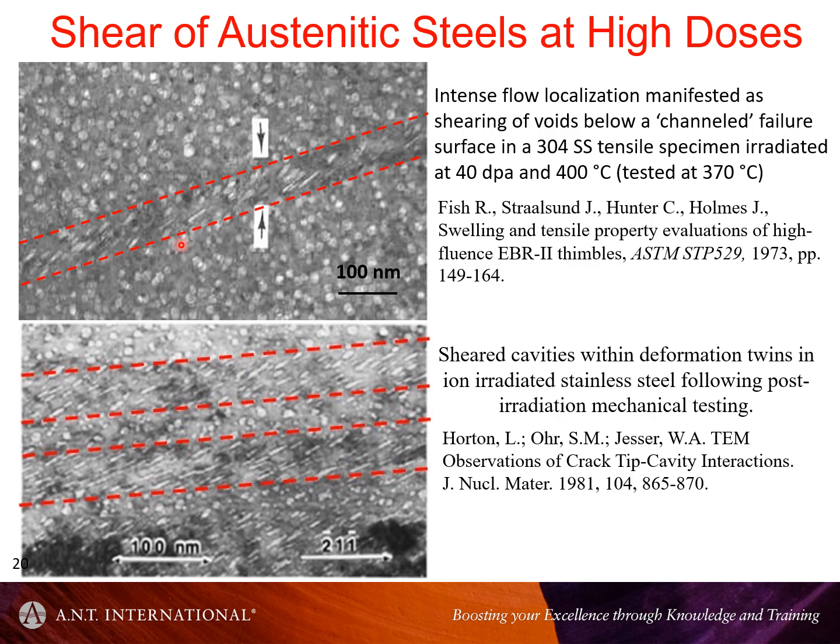You'd not see the twin material, because the first twin would go through, shear the cavities, and then let's say another twin comes through in the same volume. It'll return the crystal back to its original condition, but give the cavities an extra shear. So that would be my bet if it turned out that there was no twin here when this was tilted to the right conditions.